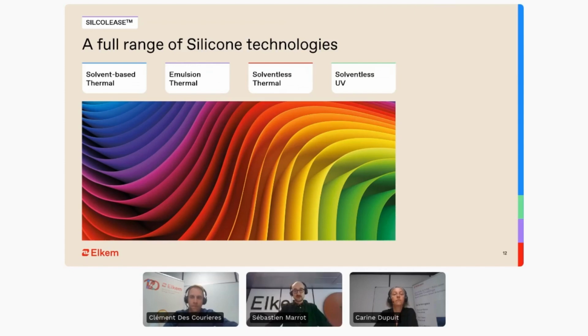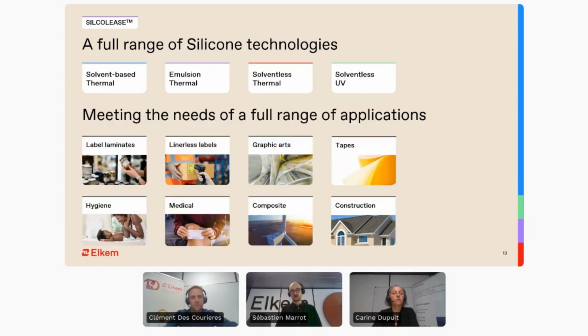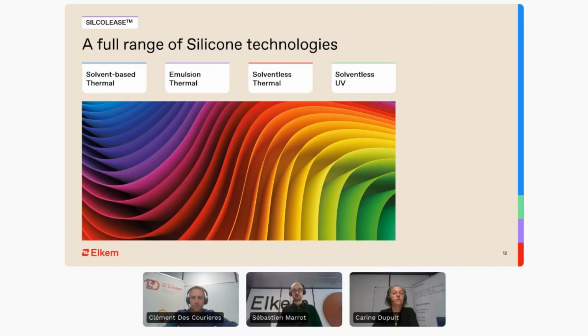Today, we offer on the market 4 complementary silicone technologies, which can be categorized as follows: solvent-based thermal, emulsion thermal, solventless thermal, and solventless UV. In other words, these systems are supplied in 3 basic forms: in solvent dilution, in water as emulsion, or as 100% silicone fluid. And you know that the choice of the appropriate carrier material will be defined by many parameters, such as the coating equipment, the substrate to be coated, and also regulatory and safety limitations, and also final end performance. And at last, the polymerization of the silicone is carried out either by a thermal curing mechanism or by UV light activation.